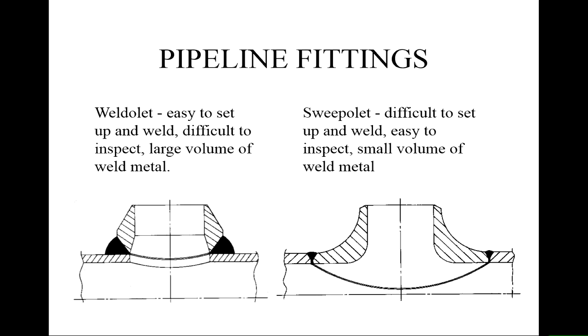So the weldolet's easy to set up and weld, but it's very difficult to inspect. If there's a crack in here somewhere, it's very difficult to find it with inspection methods. And it involves depositing a large volume of weld metal, the black part there. Basically the cost of welding is proportional to the volume of weld metal you need to deposit, so it costs a lot of welding time. The sweepolets are much more difficult to set up because you've got to match these things up more precisely, but the welding time is relatively short, small volume of weld material, and it's very easy to inspect. You use the same line pipe inspection techniques that you have on site. So if you can do it, it's best to have a sweepolet, but the fallback position is the weldolet in most cases.